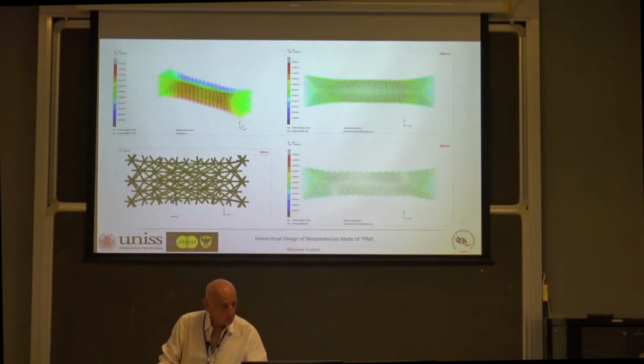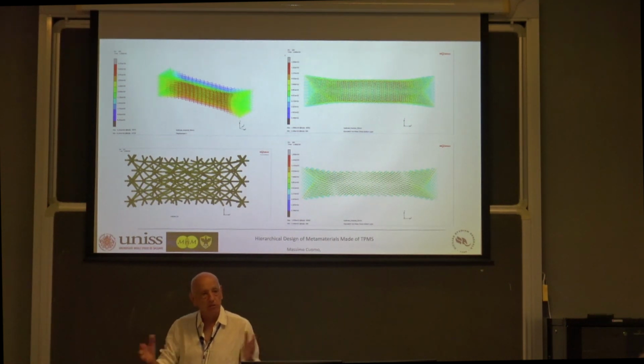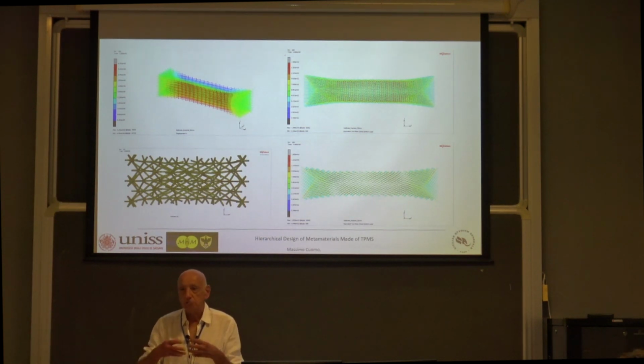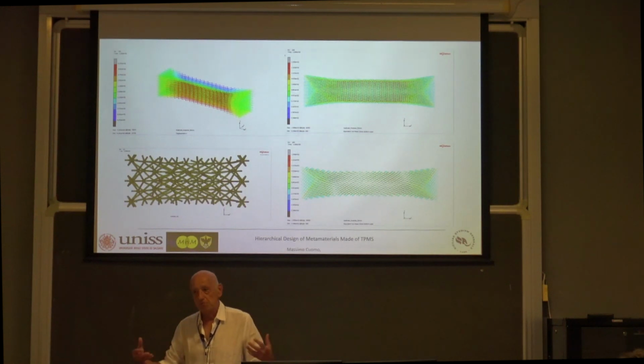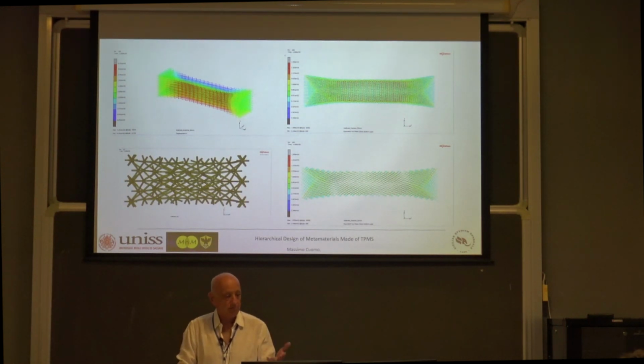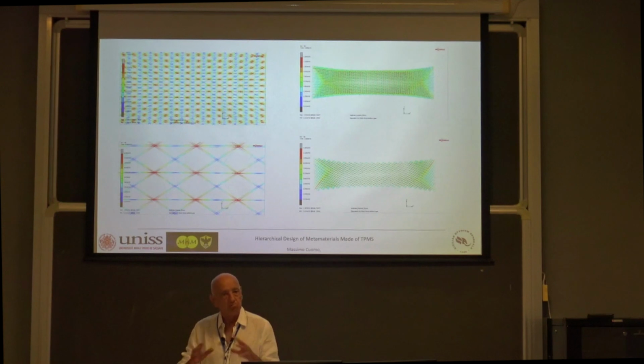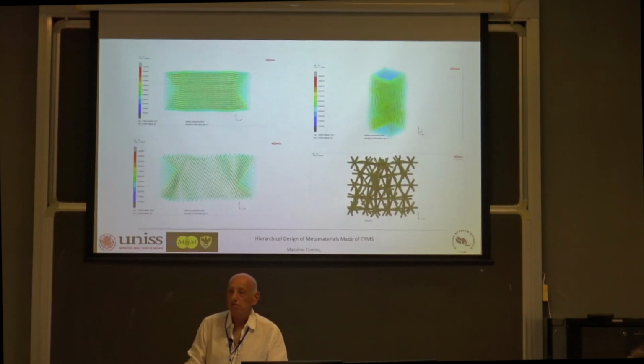And so we did some simulations, in extension and compression. In the simulation, we could develop rather large deformation due to the fact that the plasticity would spread almost throughout the whole specimen before getting to rupture. In this image, the red spots are plastic areas. This can be seen in some detail. The plasticity was spreading, of course, at the joints. Those are rigid joints. Similarly in compression, the deformation shows some bands due to the boundary conditions, which were clamped.